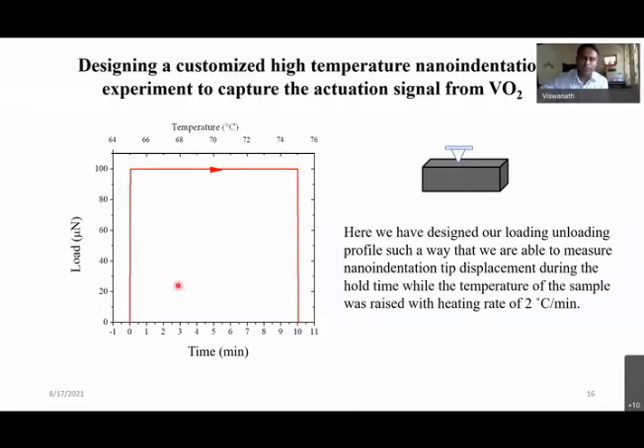Nano indentation, of course, I will explain in a little more detail how we can measure the mechanical properties. In this case, it's a sharp tip, extremely sensitive. I'm going to just keep the tip on and just make contact on my sample. So we have taken vanadium dioxide micro beams of around 50 micron in thickness, and length can be even millimeters to probably 500, 600 micrometers. I know by EBSD what exactly the orientation of the facet is.